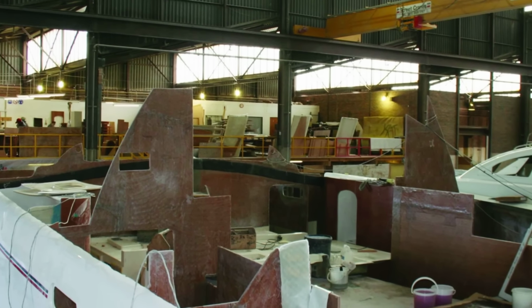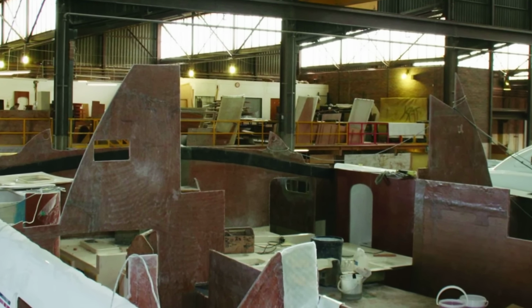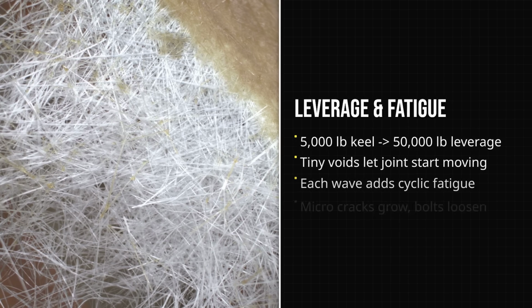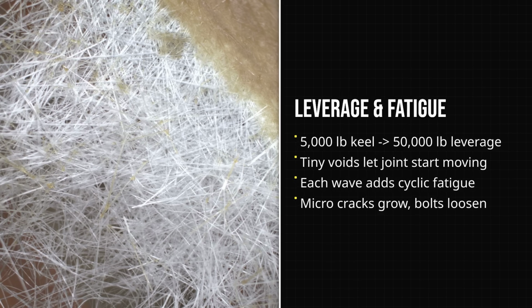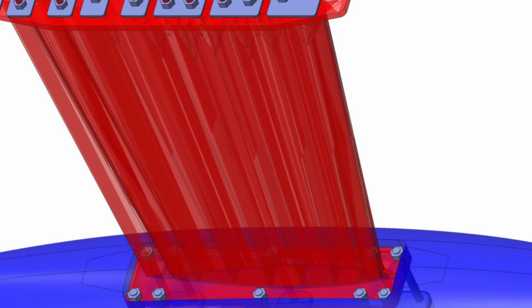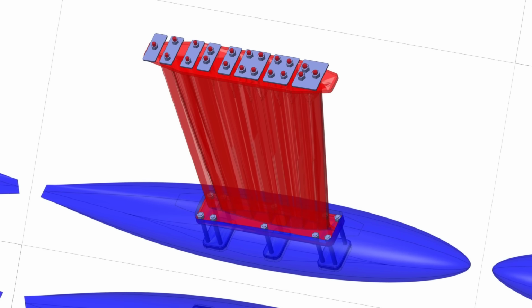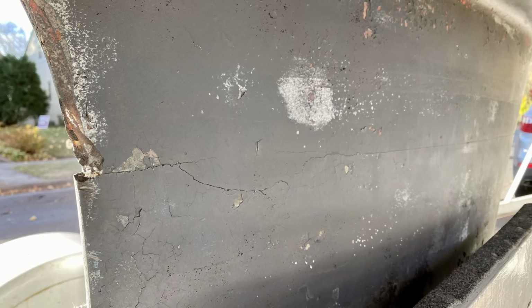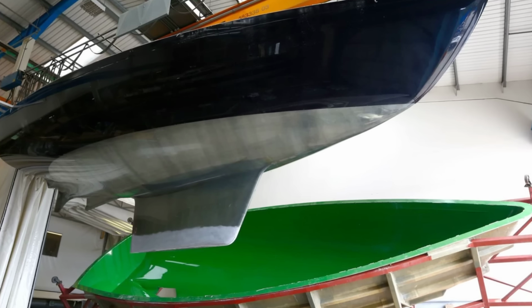The hull stub and internal grid are designed to spread these forces, but when loads reach this level, even a small flaw, a void in the laminate, a crack in the bedding, can let the joint move. The Catalina Smile at the keel seam is the outward symptom, but inside, stress works on the bolts, the stub, and the grid. Over time, the joint loosens, water seeps in, and the cycle accelerates.